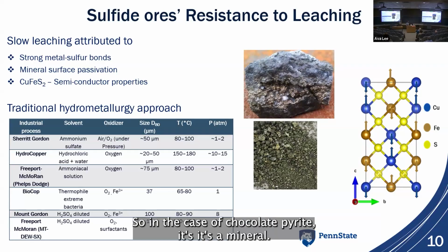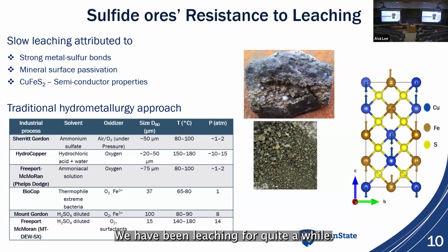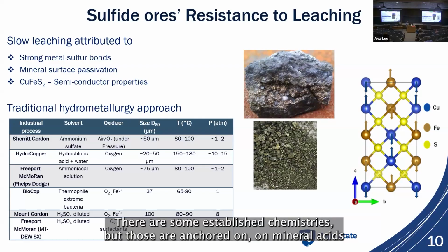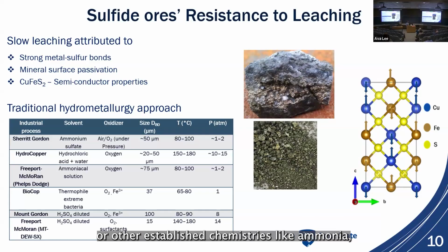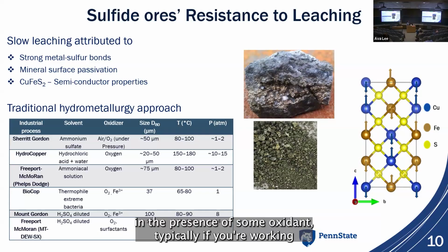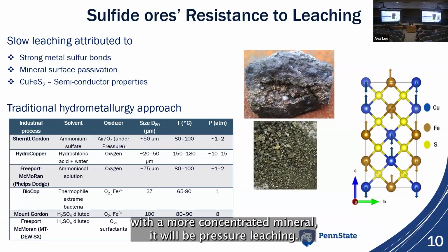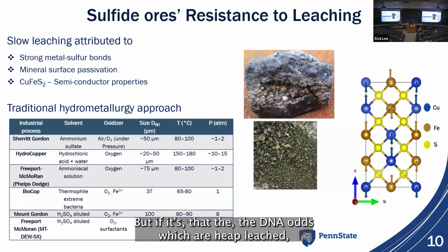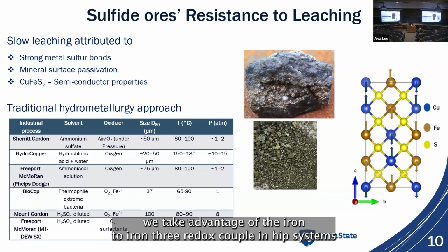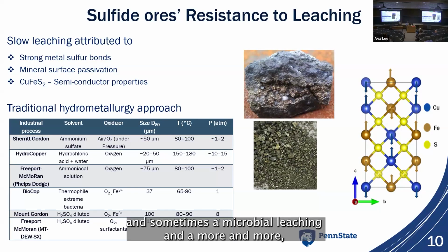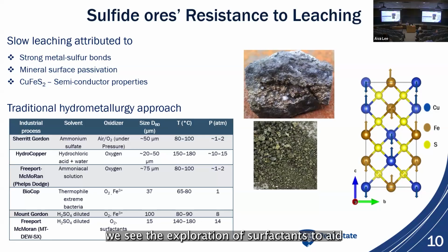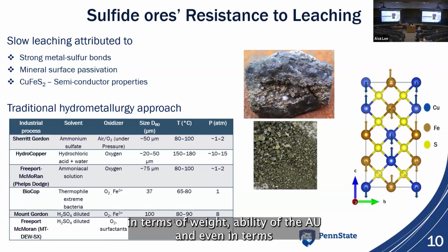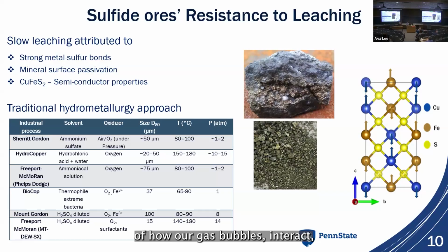So in the case of chalcopyrite, it's a mineral we have been leaching for quite a while. There are some established chemistries, but those are anchored on mineral acids or other established chemistries like ammonia in the presence of some oxidant. Typically, if you're working with a more concentrated mineral, it will be pressure leaching. But if it's the leaner ores, which are heap leached, we take advantage of the iron 2, iron 3 redox couple in heap systems, and sometimes microbial leaching. And more, we see the exploration of surfactants to aid the wettability of the ore, and even how our gas bubbles interact in our system when introduced.